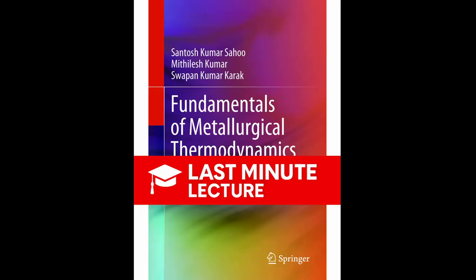And this leads to a really powerful realization about how G fully defines the system's state. If we look back at that equation, dG equals minus SdT plus VdP, we can derive the partial derivatives from it. Can you tell us why these are such amazing shortcuts? They're truly elegant. If we hold temperature constant, the dP term goes away, and we find that the rate of change of Gibbs free energy with respect to pressure gives us the volume. The partial of G with respect to P at constant T equals V.